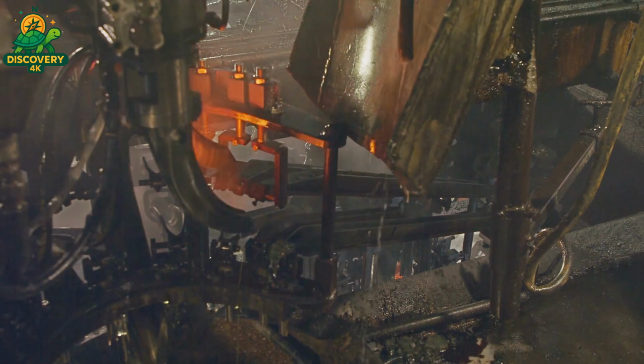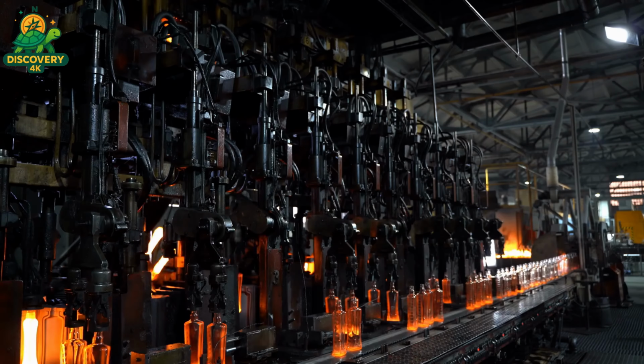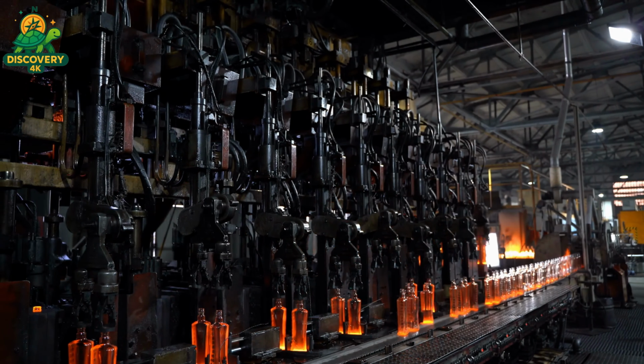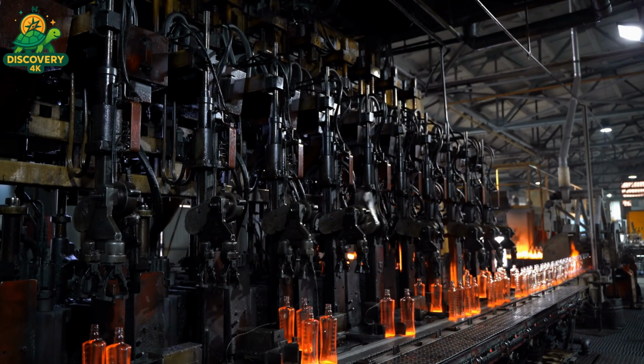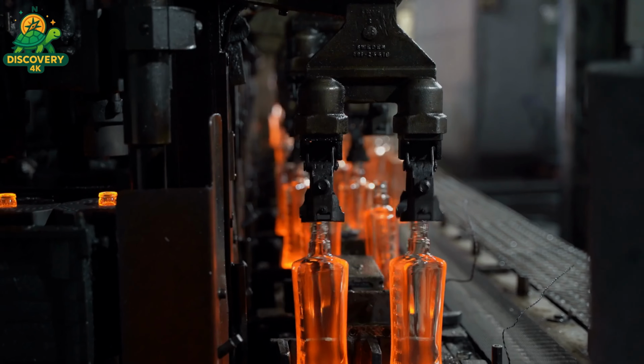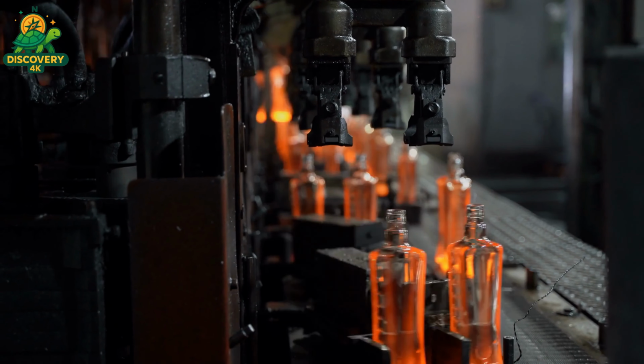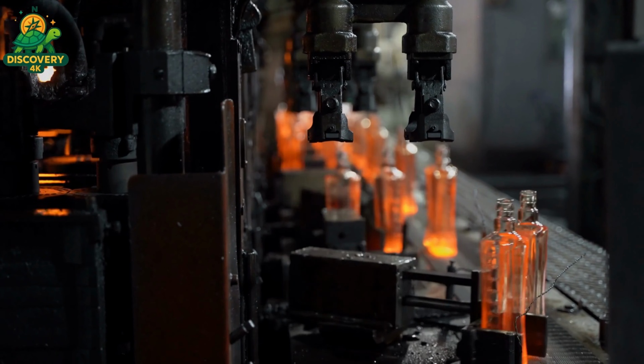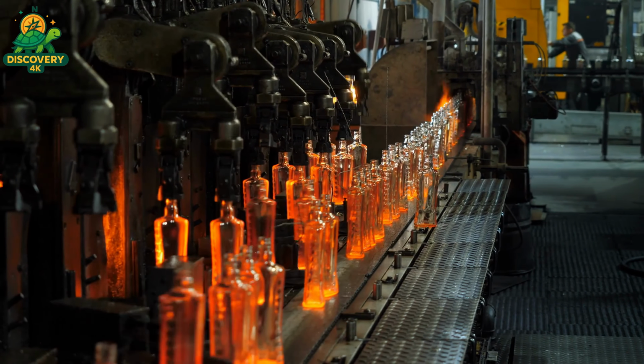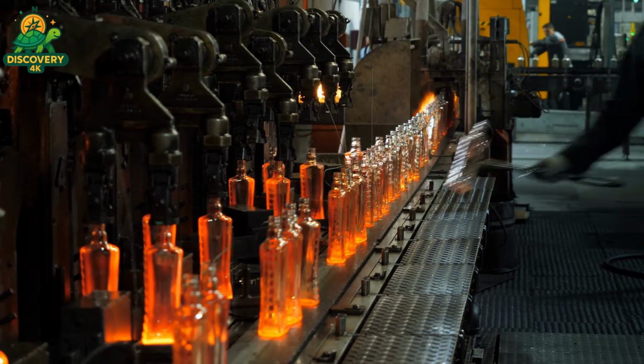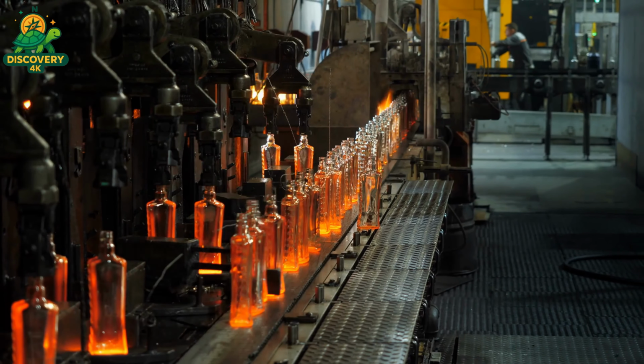Step 3. Final blow molding. The parison is then transferred to a final mold, which gives the bottle its full shape: neck, body, and base. A blast of compressed air inflates the parison until it perfectly conforms to the mold cavity. The bottle's defining features, branding, ridges, threads for caps, are all imprinted at this stage. This entire sequence takes less than 10 seconds and it happens over and over, with remarkable precision.